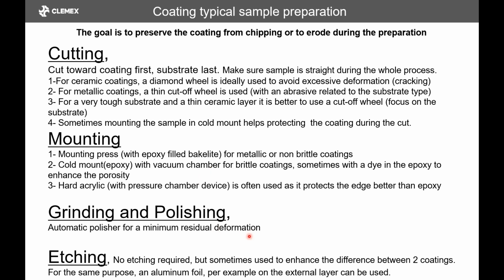Grinding and polishing, it's much more efficient and better to work with an automatic polisher, because it will help prevent mating faces, so that you will have a straighter coating or a more perpendicular coating. So when you put it on the system, you won't have any angle, or it will be minimized anyway.